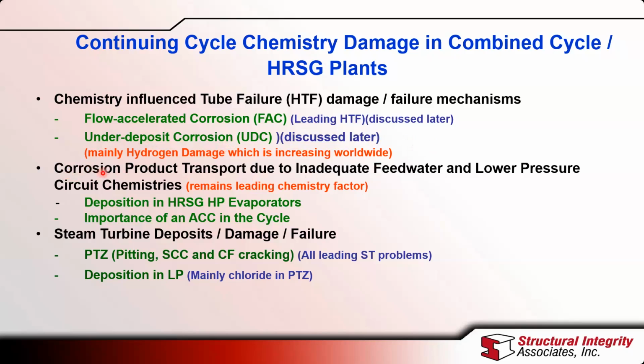The second major area are the corrosion products. This is basically the total amount of iron that's transported from having inadequate feed water and in the lower pressure circuits of the HRSGs. And this, as you'll see a little later, is the leading chemistry factor which is not addressed properly. As a result, this ends up with deposition in the HRSG evaporator, which is one of the precursors for the under deposit corrosion mechanism.